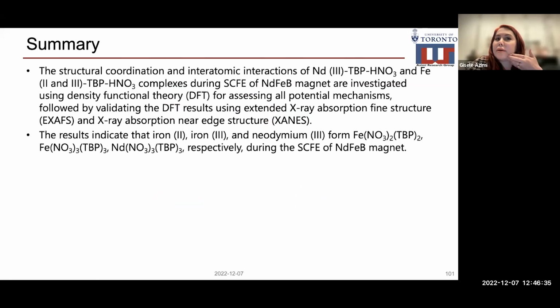We looked at the structural coordination and interatomic interactions in the neodymium 3 TBP HNO3 and iron 2 and iron 3 TBP HNO3. And we performed density functional theory calculations to assess all potential mechanisms that I showed in the previous slide. And we validated these results by extended X-ray absorption fine structure, which is called EXAFS, and X-ray absorption near edge structure, XANES. This is the first time that these structures are characterized using this advanced technique. The results indicated or proved that iron 2 forms iron nitrate 2 TBP2, iron 3 forms iron nitrate 3 TBP3, and neodymium forms neodymium nitrate 3 TBP3, as we exactly predicted in our preliminary